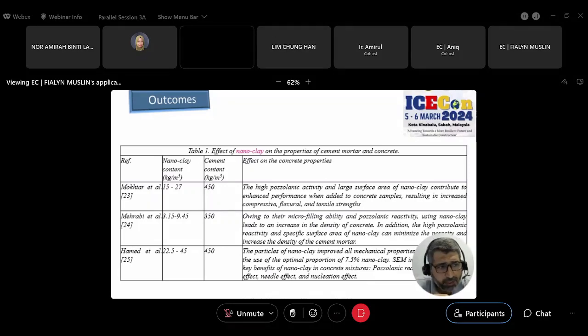Another study by Mehrabi also showed that the use of up to 9% of nanoclay in almost 350 kilogram per cubic meter cement content, they observed that owing to their microfilling ability and pozzolanic reactivity, the use of nanoclay leads to an increase in the density of concrete. In addition, the high pozzolanic reactivity and specific surface area of nanoclay can minimize the porosity and increase the density of the cement mortar.